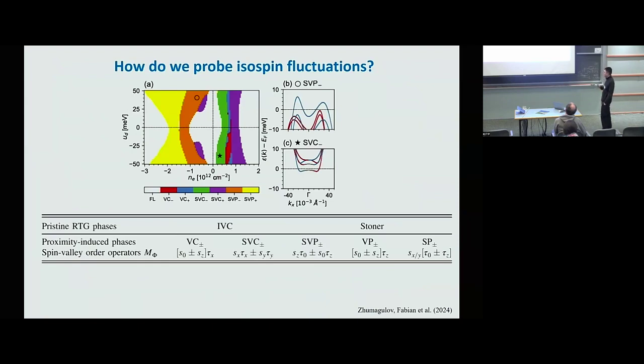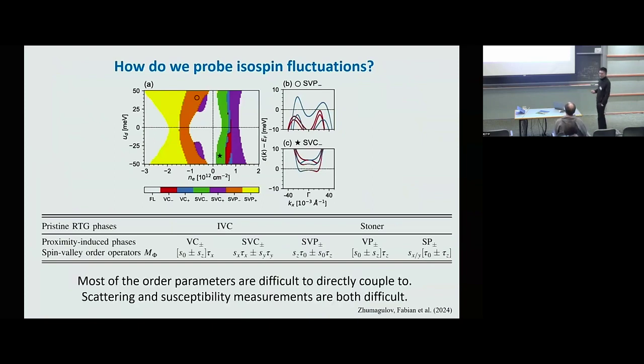So we can think about what's the typical way experimentally we probe fluctuations in condensed matter. Typically there are two ways. One is scattering, the other one is susceptibility. But both of these two ways require that we directly couple to the order parameter. For example, if we want to measure susceptibility, we have to drive the order parameter, couple to it and see what's the response of the system. But it's unclear how we can do it here because some of these order parameters are quite exotic, and it's unclear how we could couple to them.